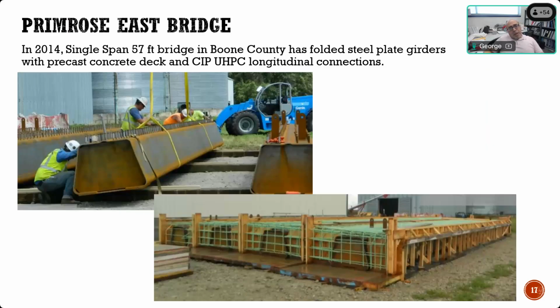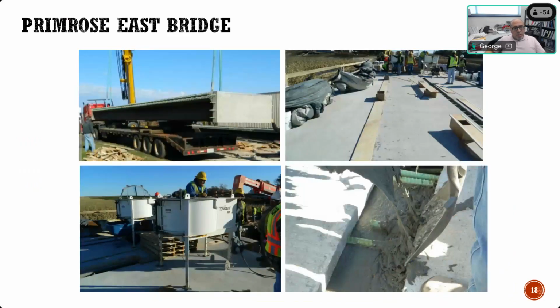And that's the Primrose East Bridge, where they used the UHPC for connection between precast segments. So in this project, it had folded plate steel girders with a conventional concrete deck cast on top of them, and also a diaphragm. The girders were 57 feet long, and they had, I think, 4 of them, and they put them side by side, and then used UHPC to fill the longitudinal joint between the segments. And this is a picture here of how the segments look.